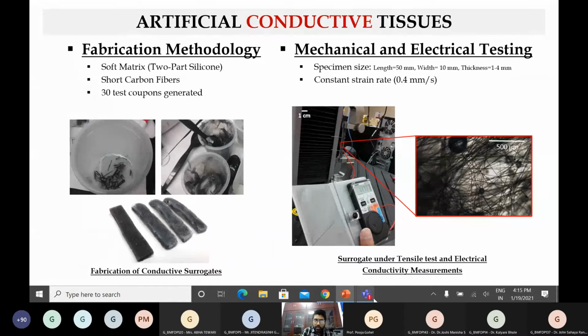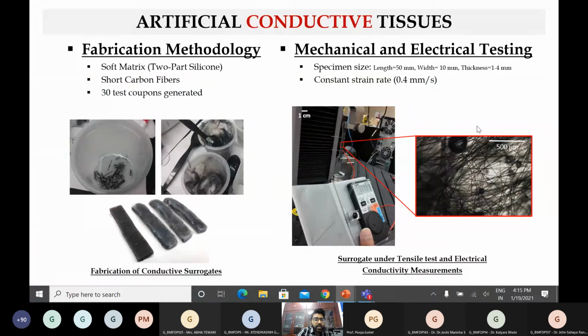So how do we, I'm just going to quickly check to make sure everything is going fine. OK, great. So how do we make this? The first step is a soft matrix. It's a two-part soft silicone. We cut short carbon fibers. So we get strands of carbon fibers, which usually come in a roll. We cut short carbon fibers and disperse them within this media and mix them really well.